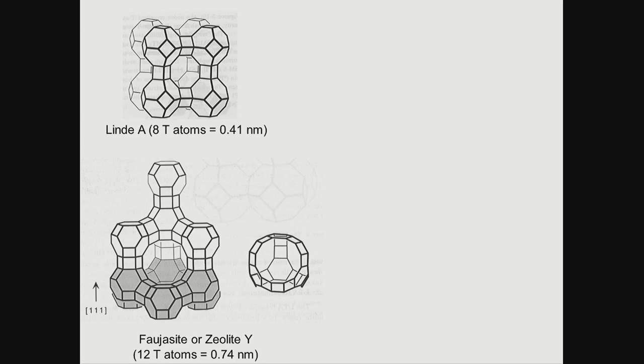However, what is important about this one here is it's got a massive internal chamber, and that chamber causes problems, but it also means it's like a pressure cooker. So it will allow small molecules in, they will react, and they will do something on the inside, which means this catalyst is prone to deactivation, but it just happens to be the major use in FCC, which is fluid catalytic cracking and the production of gasoline. Those 2 zeolites are responsible for, number 1, the biggest bulk use, and number 2, the most expensive.